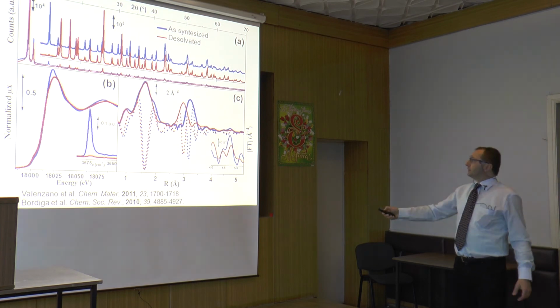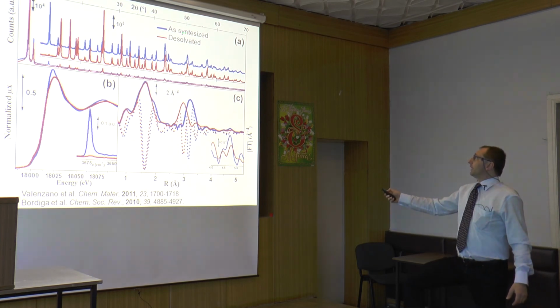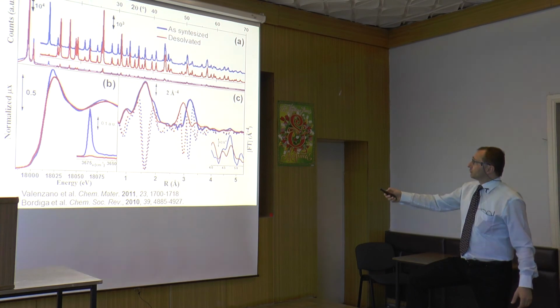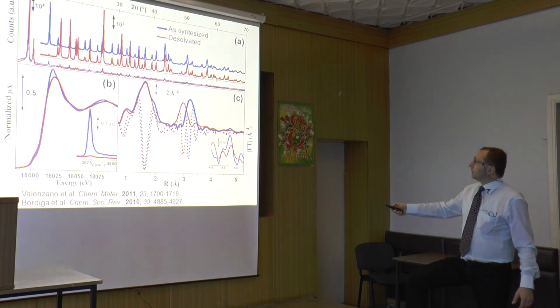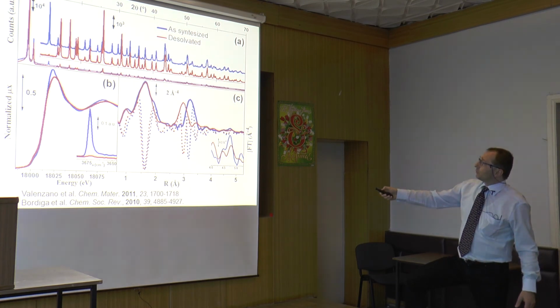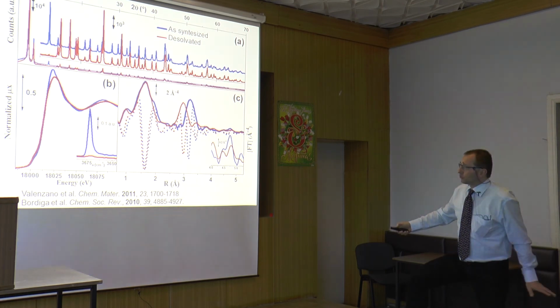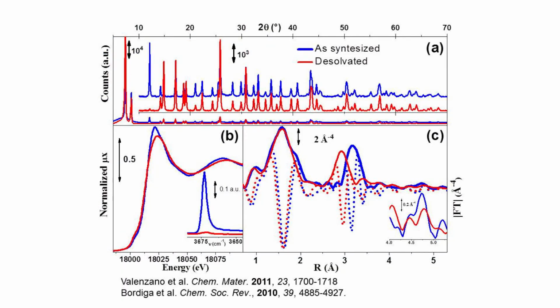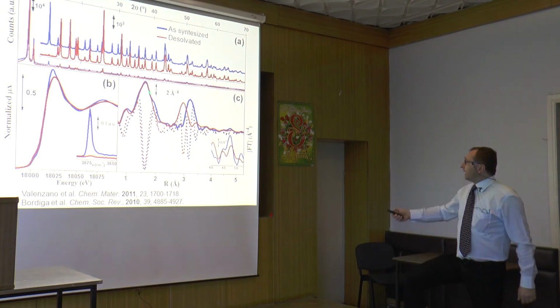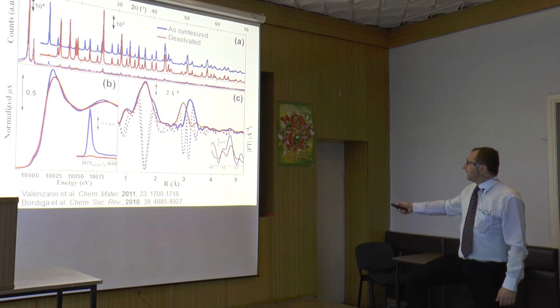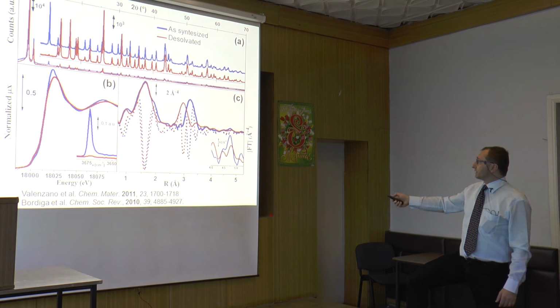Again, these are the diffractograms of the as-synthesized in blue and the desolvated material. You see exactly the same peaks. You just see that this peak here is of low intensity. That's typical of porous materials, where you are removing the disordered electron density inside the pores. The basal peaks go down in intensity. This is known in zeolites as well. And then here, this is the EXAFS. So you see a small difference here, but a huge difference here and there.